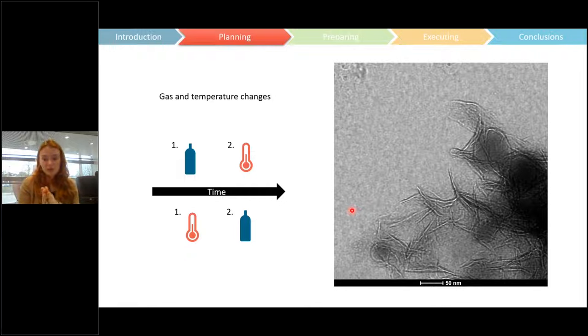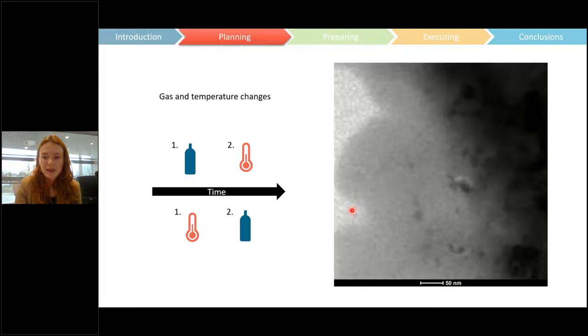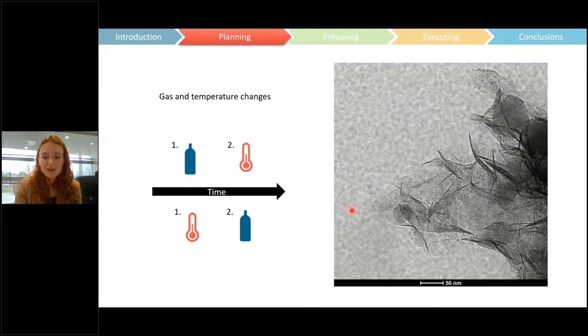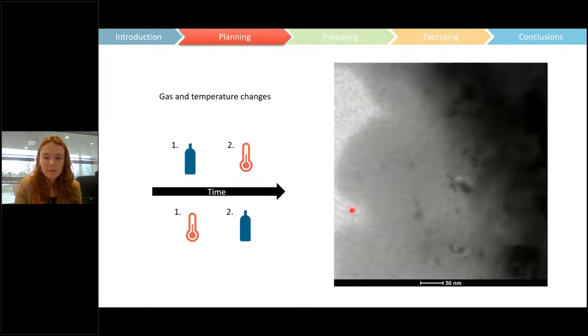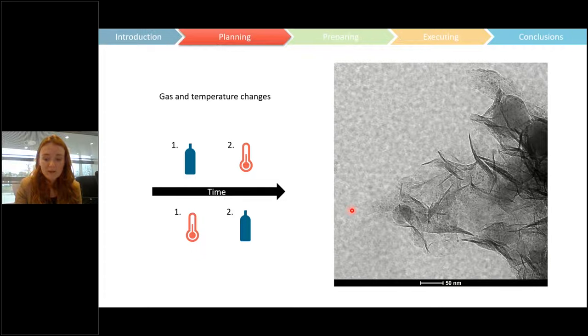So I'm going to show you a video. The video on the right now is about to play. You can see it's quite under focused at the beginning, overfocused at the beginning, but it gets better, I promise. But you're going to see what happens where I have used changing the gas to start my experiment. And you'll see that I completely lose my sample. Let's play now. See? And it's gone. And I went back. So I've sped it up quite significantly, but we go quite far out when you lose your experiment.